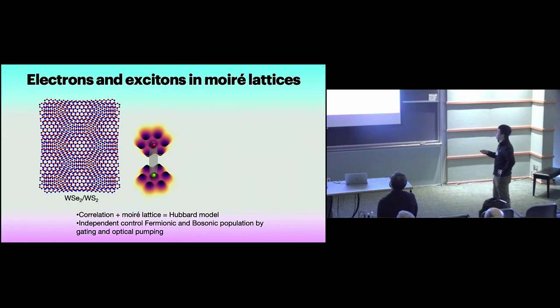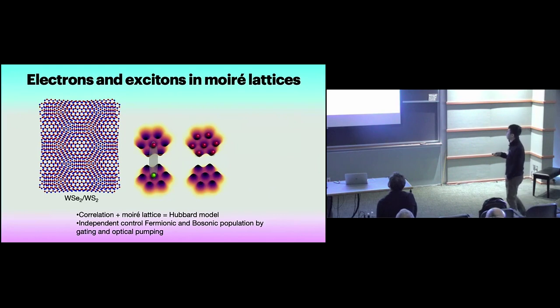The idea is that I can put electrons on this locally trapping potential, but I can also put excitons inside them. And I can control the density of the electrons and excitons independently, right? So I can apply the voltage to tune the carrier density, and I can change the pumping power to tune the exciton density. So in a simple regime where I have an empty lattice, you can create an exciton like this. But if I put 1 electron per Moiré unit cell, the next time I create another exciton, this exciton will correspond to a doubly occupied electron site.